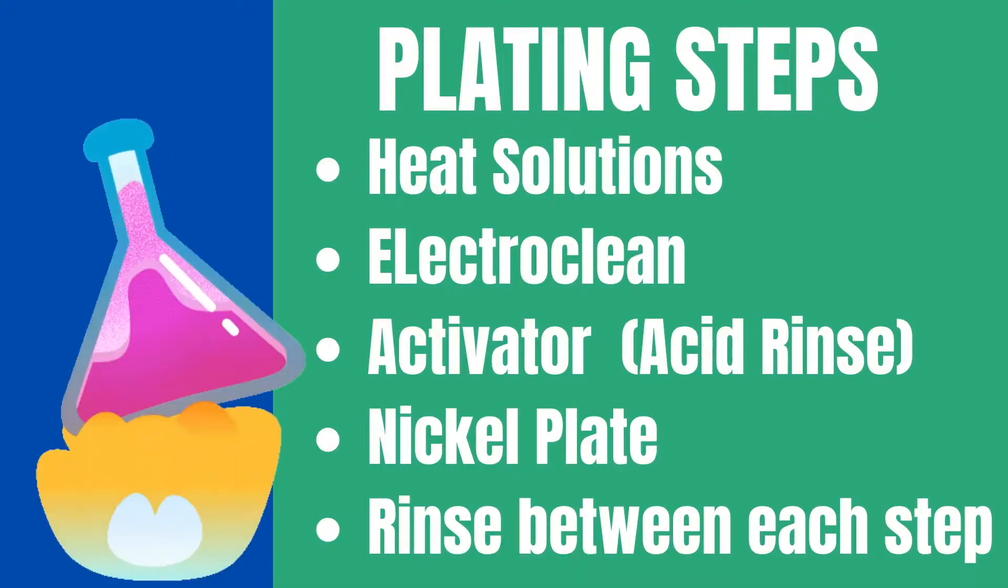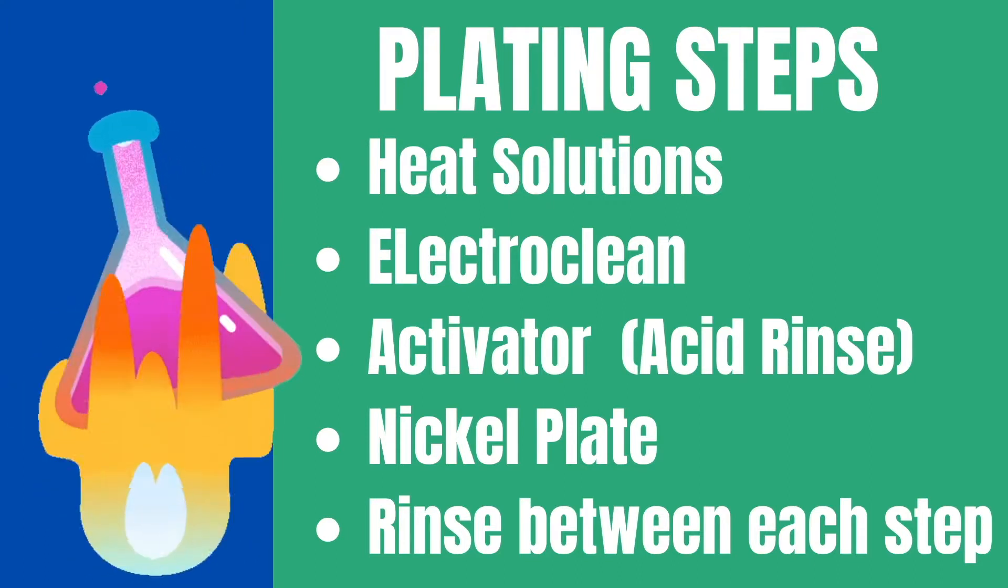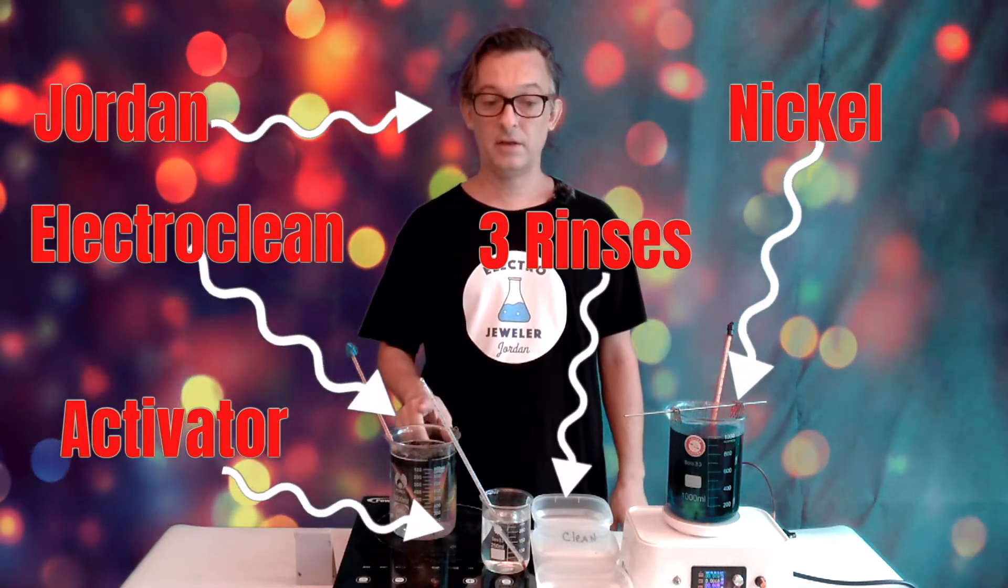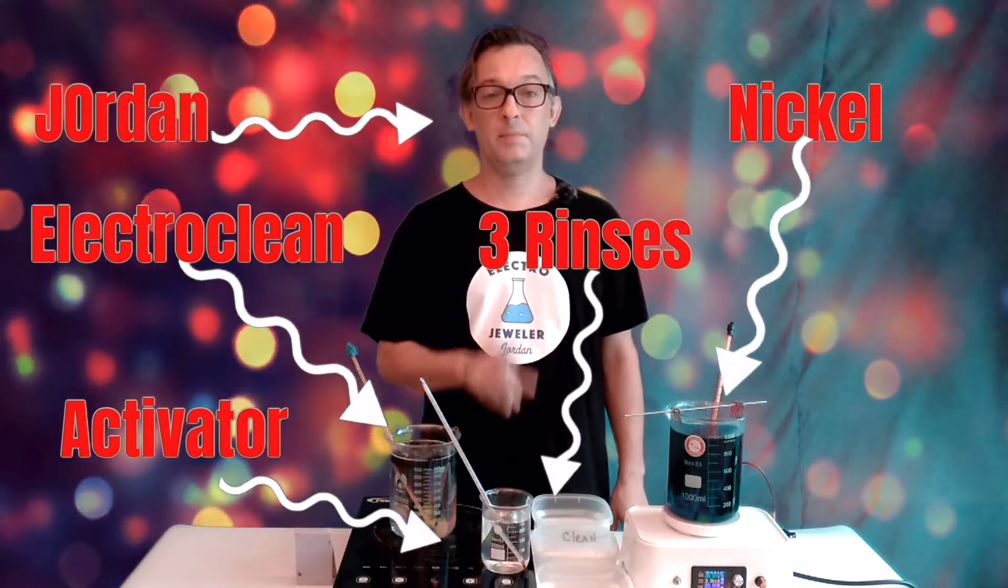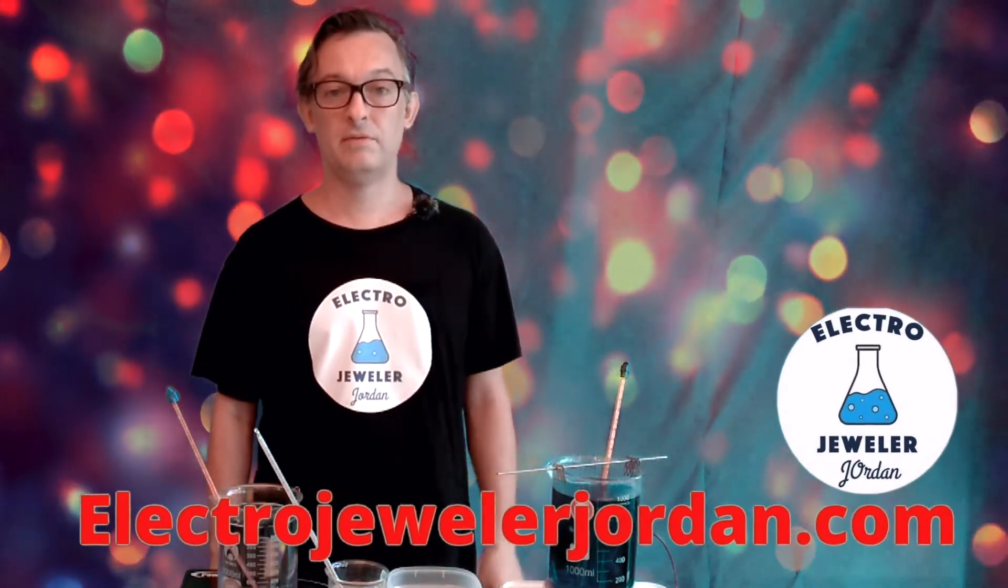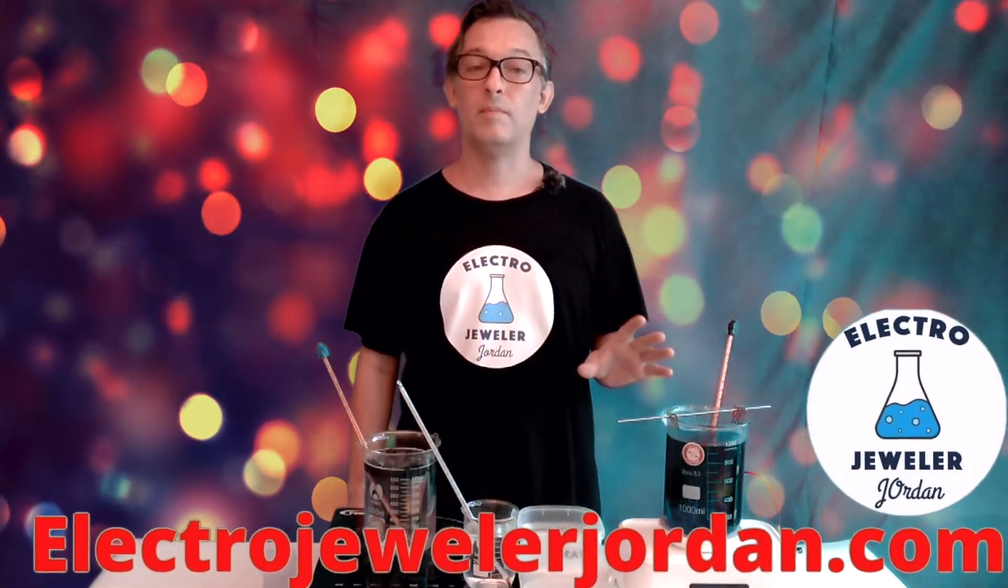First thing we need to do is heat up the solutions to the appropriate temperature. Now that the solutions are at their appropriate temperature, we are going to first electro clean, then rinse, then dip it in nickel activator, and then nickel plate for 10 minutes. 10 minutes will give you about a 1 micron thickness plating.